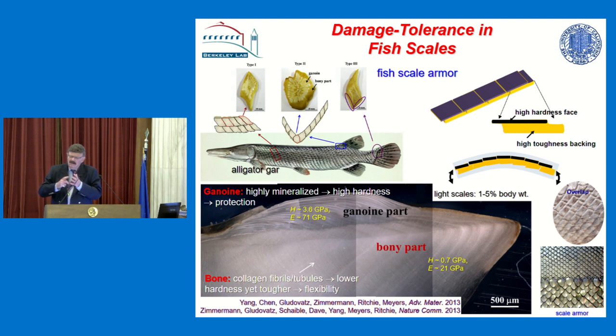So you need two regions. First, a hard region at the surface to prevent something penetrating, and then a lower region which tolerates that additional strain. And of course, fish scales are like that. This is the hard region of a scale. This is of an alligator gar fish. This has a much, much higher stiffness and a much, much higher strength. It's all collagen and mineral, but it's much more mineral up here. And below it, less mineral, more collagen, is the tough region.